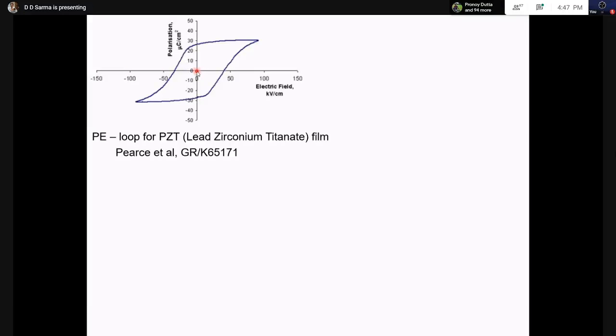And what the polarization does, first of all, very important to see that it has a large polarization even when I don't apply any external field. So there's a remanent polarization. That remanent polarization goes up a little, shows a hysteresis, closes the loop, and beautifully does this. This is exactly like in magnetization. You have a BH loop. A ferromagnet will show you a BH loop. A ferroelectric will show you a PE loop, polarization versus electric field.